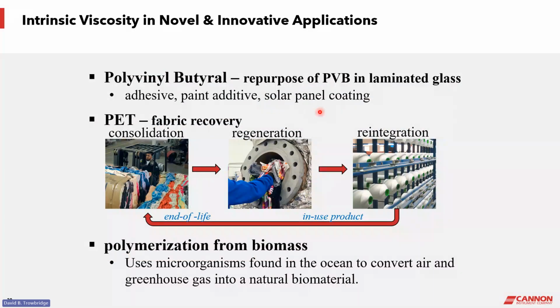I wanted to mention some innovations that we are applying to intrinsic viscosity determinations. There's this recycling of polyvinyl butyral. You can go to different applications after recovering it from laminated glass. It's that plastic film that's inside safety glass, and you can recover that and apply it to different applications, but that's going to be based on the intrinsic viscosity. So there's an important application for recycling this material. And it's also done in other cases.